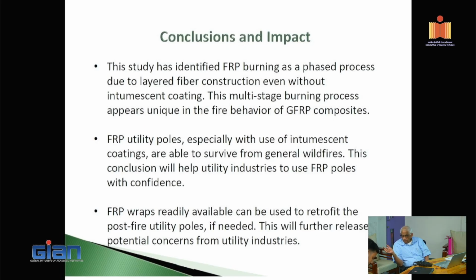So how can you correlate that to FRP bars? All I can say is if I expose an FRP bar to a fire of 1100, let's say the 1/4 inch bar, as I said, say 40 layers. So each layer is 1/160 inches thick. So all I'm saying is 1/160 inch thickness is 10 seconds to burn through. Now your 1/4 inch bar will take about roughly 30 minutes. That is without the concrete cover. With the concrete cover, you get a better value. Okay, so that gives you a quick presentation.